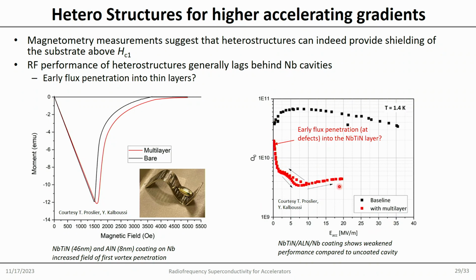However, if you look at that in radio frequency, quality factor versus accelerating gradient with a multilayer, it doesn't look very good. The losses are huge, unfortunately. So it does not work in a radio frequency field so far. So what do we think is happening? We think that probably the surface layer allows some flux to enter, so this doesn't really work.